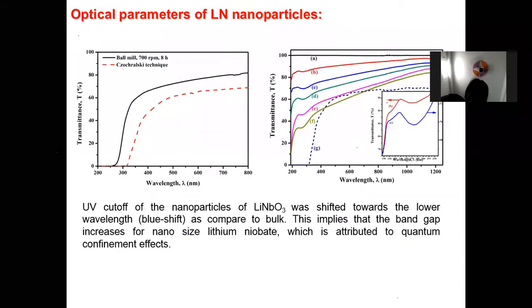So this is the optical absorption to see whether this will be used for that particular application, because it shows the band gap. The band gap should be in such a range that it should not interfere with the device, because we are using it for an optical device. So SHG, second harmonic generation, is an optical device. So the band gap should be in the range. This UV cut shows the band gap of the material.